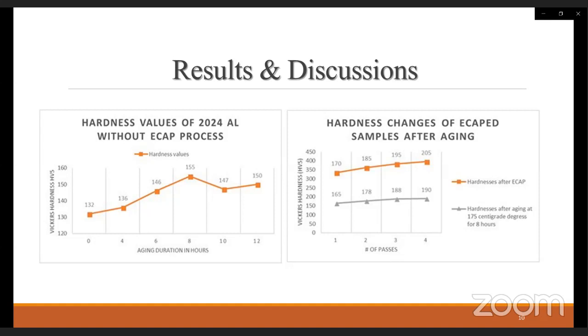the hardness values are increased directly proportional to the ECAP pass number. So on the right side, right graphic, we can see the hardness increasing with increase of the number of passes. After the aging operation, the hardness values of the samples which are not ECAPed are increased. The hardness values of the samples which are passed through ECAP are decreased.